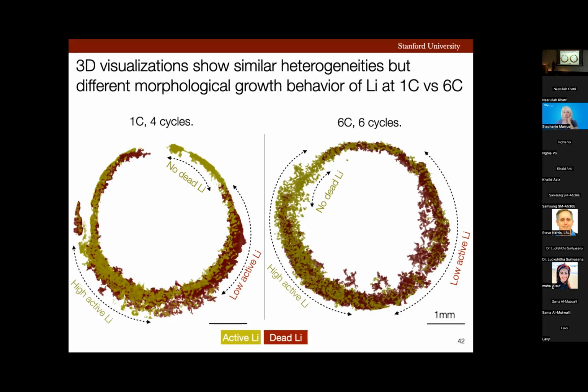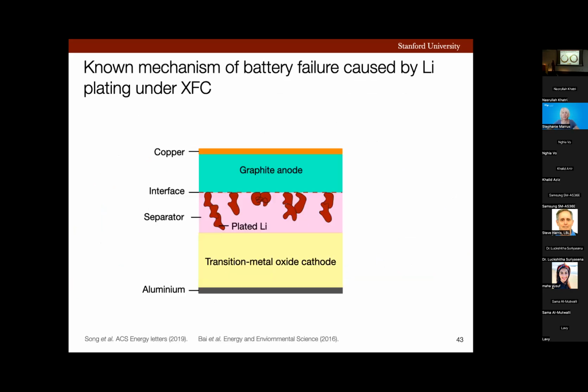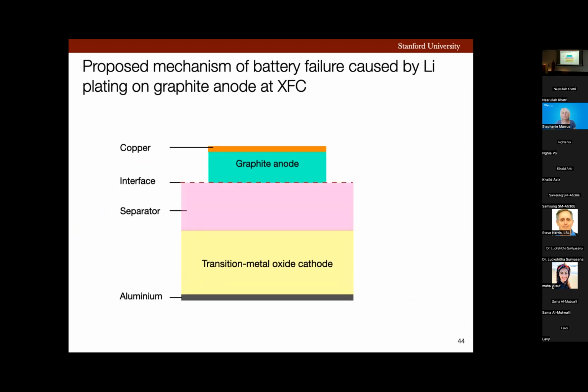So there are similar spatial heterogeneities. However, there are different morphological growth mechanisms of plated lithium at 6C versus 1C. For example, at 6C, we do see these sharp tip growing features that seem to be propagating towards the center of the graphite anode. However, at 1C, we see this mossy root growing structure, which seems to be propagating outwards away from this structure. Now, the known mechanism of battery failure caused by lithium plating is that lithium plating initiates at the interface and then forms structures that grow through the separator. My work has shown that it's much more complicated than that.